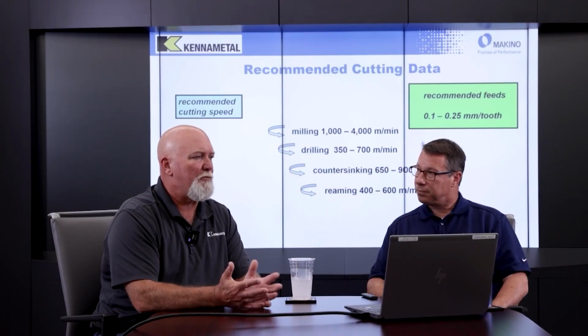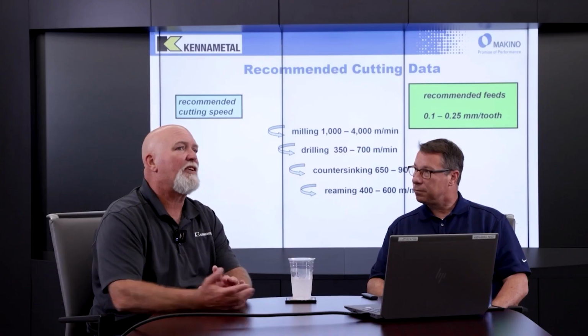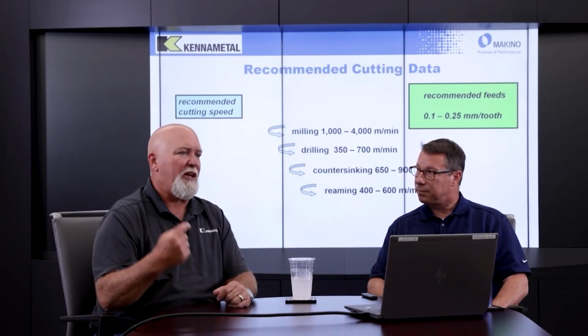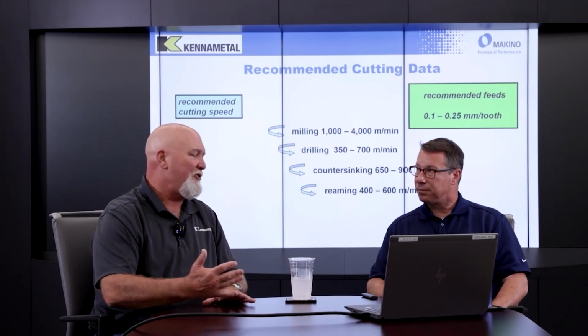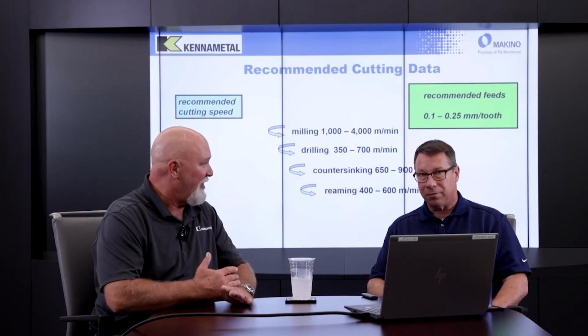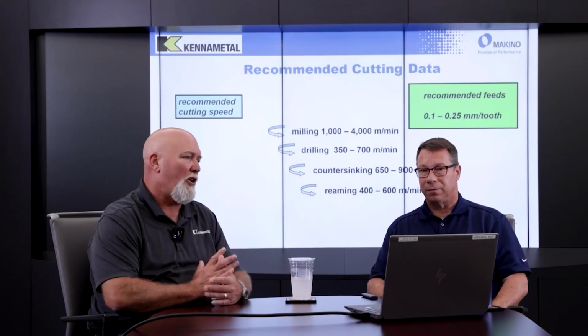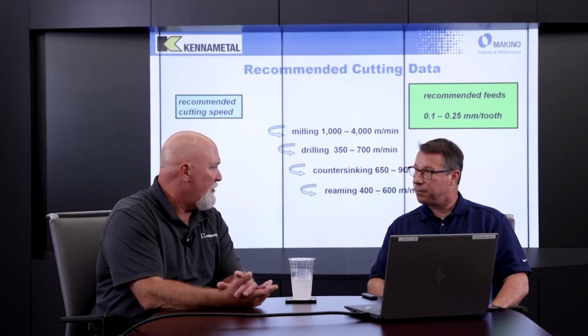Generally, the failure mode in milling, or what we want it to get to, is burr formation at end of life. And what I typically see is that people think PCD and they think fast, so they run high speed, but they think it's fragile and they need to run low feed. And that's somewhat the death knell of it. That's how to produce a burr very quickly using PCD. So the higher chip load when we're exiting the part tends to cut cleaner coming off the edge, and we can run longer without producing that burr.